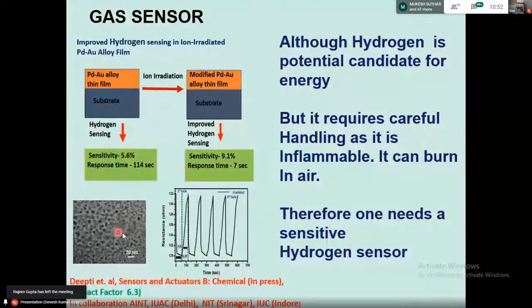And this is a picture you can see of the nano alloy film, the nanostructured film, the TEM picture. And here basically this is the response. That means when you put hydrogen gas in, its resistance increases, and when you remove the hydrogen, then it goes down. Then you put it again, it goes up again. So you can see this is very sensitive to hydrogen. This is the work of a student, Deepti, and it was published in Sensors and Actuators in 2019.